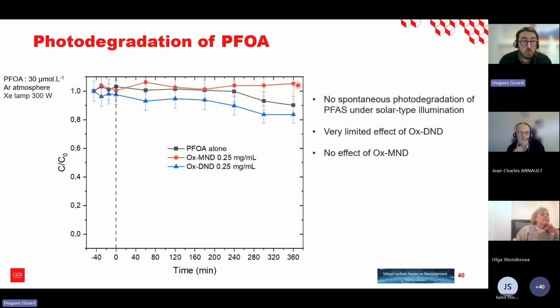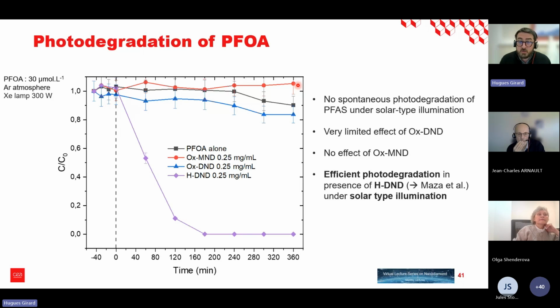But when we used hydrogenated detonation nanodiamonds, as in the pioneering paper of Maza, then we were able to reproduce the effect with this very nice decrease of the concentration of the PFOA, which is measured all along the exposure time, okay? But in that case, it is important to say that it was not with a 254 nanometer lamp, it was with a solar type illumination with our xenon lamp.